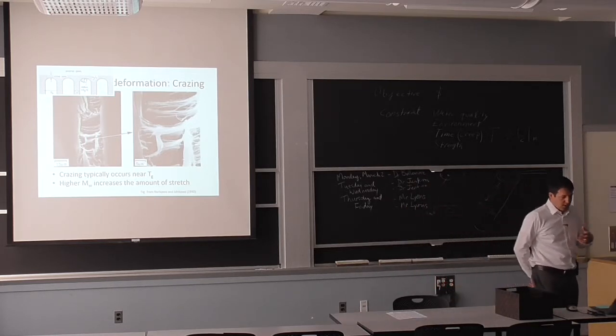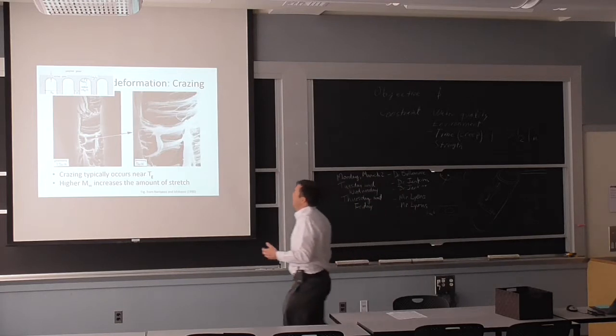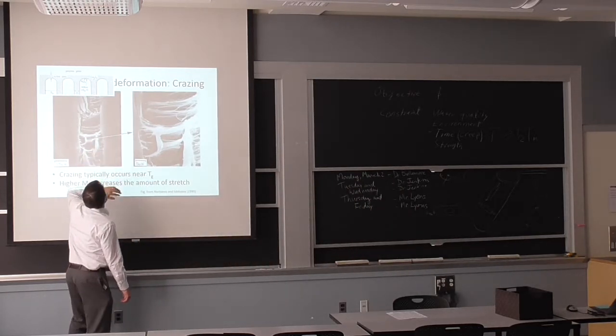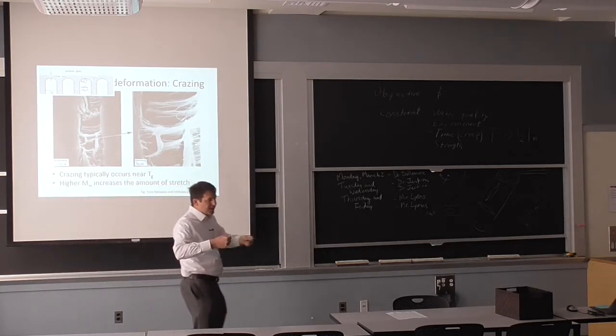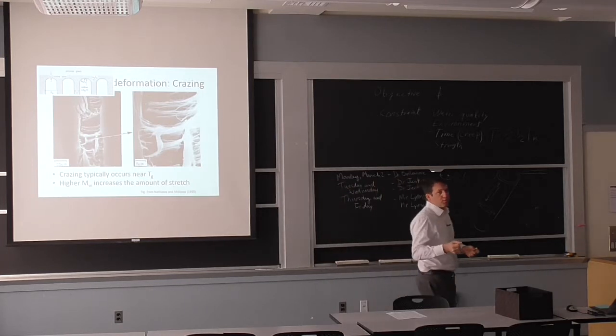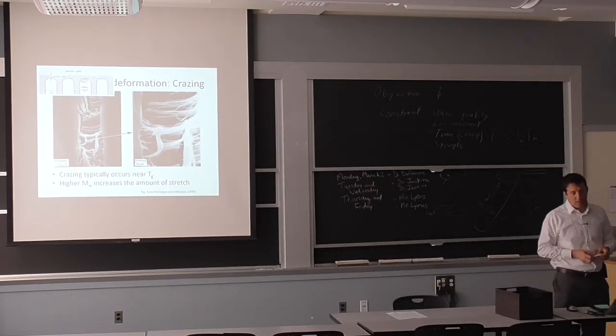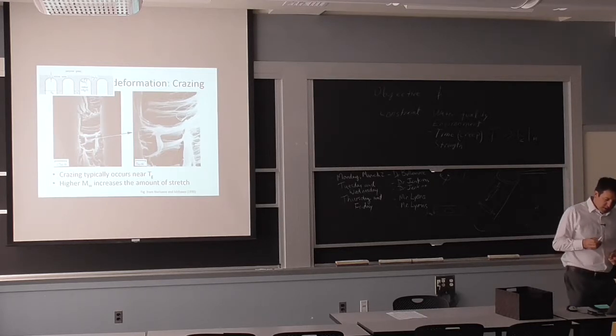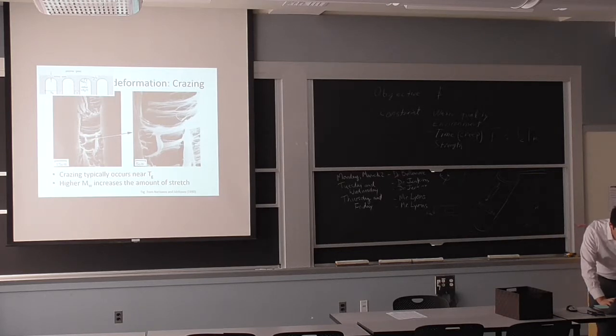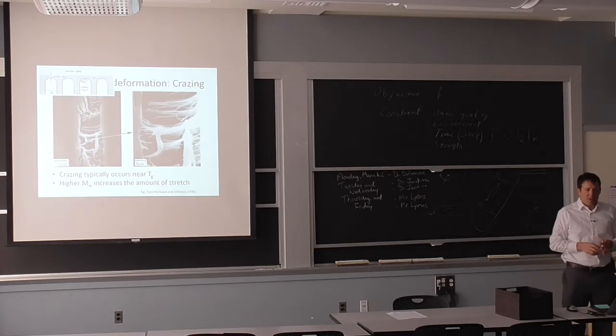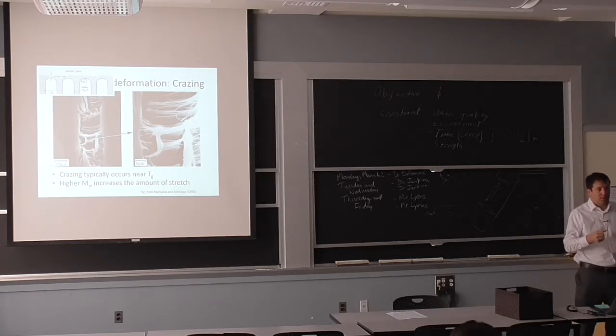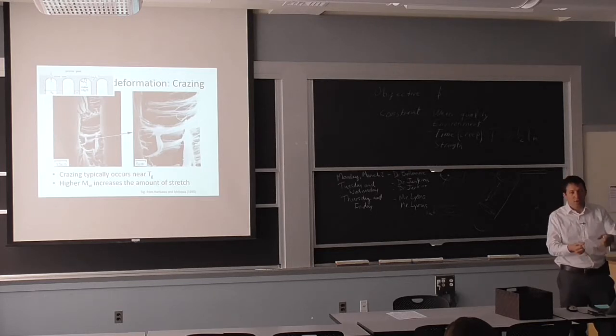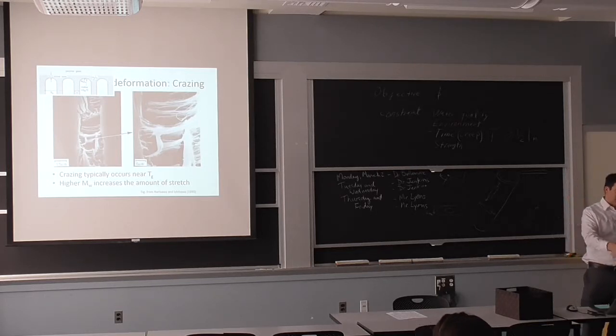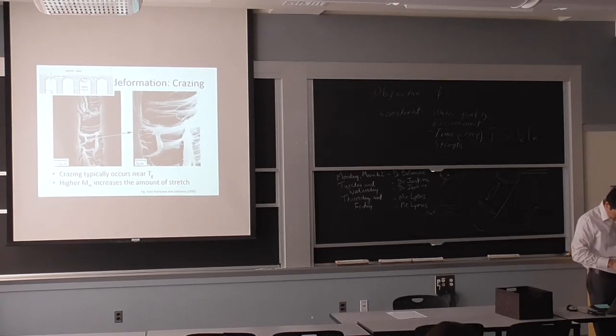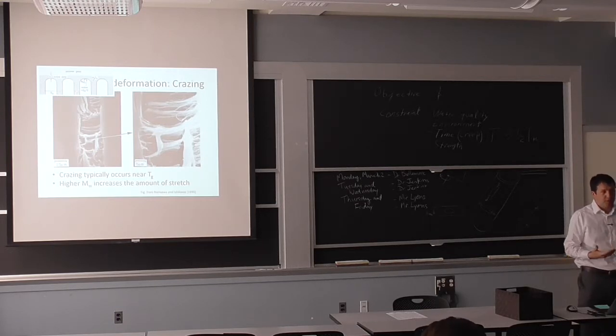For the same reason that you have creep in these materials. So at the very, very edges of these crazes, the material over time gets the opportunity to slide, and essentially you separate the macromolecules as opposed to breaking them. And that's how the creep really takes place here. The reason I emphasize this, and it's written on the slide, is if I have longer chains, sometimes maybe it's not going to be as strong when I pull on it because I don't have as many crystallites, for example. It's a different arrangement, so it may look softer if I do a pull test. But if there's a craze in it, it's not going to propagate, it's not going to be growing as easily because I can't separate these chains. They're just much longer.